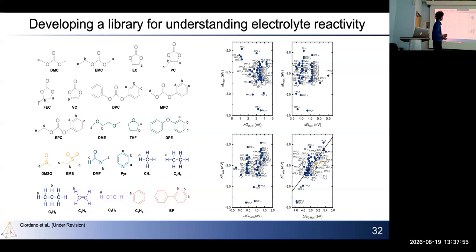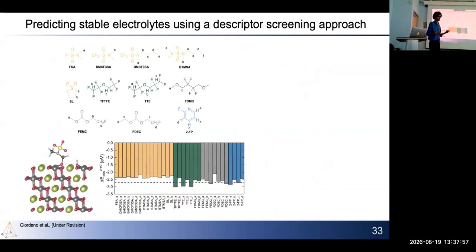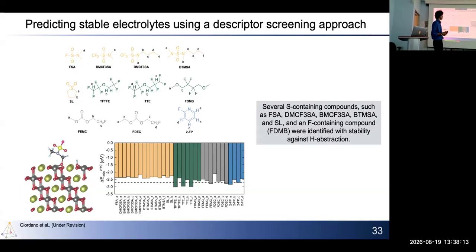With this linear trend, we are able to predict a whole bunch of new electrolyte molecules that would have lower reactivity than the current state of the art. For example, we've identified a bunch of sulfur and fluorine containing electrolytes that are potentially better performing than ethylene carbonate, which is the currently used electrolyte.